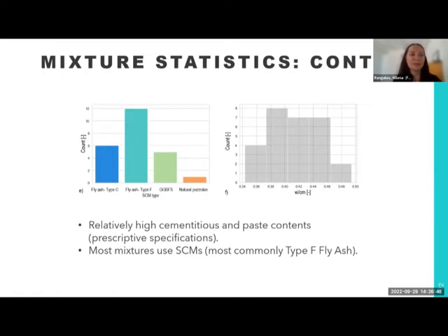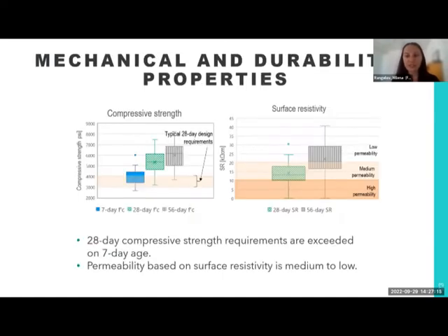And then water to cement ratios are ranging between 0.35 and 0.5. And this is important for durability consideration. I could also add that this is kind of a broader range. Probably some improvements are possible in that regard. So the main takeaways are that we have relatively high cementitious contents as well as paste contents, typically due to some of the prescriptive concrete specifications.